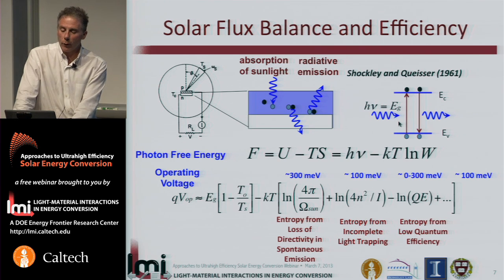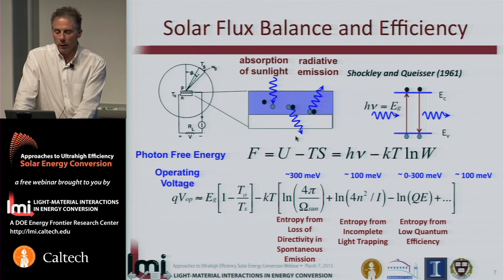thermodynamic Helmholtz free energy balance, in which we can separate the internal energy that's created by charge separation of electron-hole pairs across the band gap, and entropic terms that actually reduce the free energy of charge separation and therefore the operating and open circuit voltages of the cell by several important entropic features in the operation of the cell. And so what we can see upon more detailed analysis is that there are increases in entropy of photons as they are absorbed and emitted from a cell by changes in the distribution of directions.